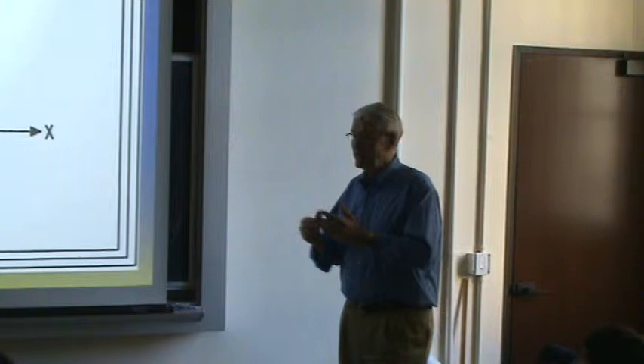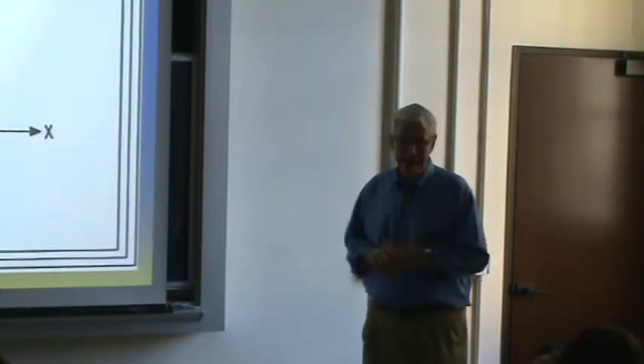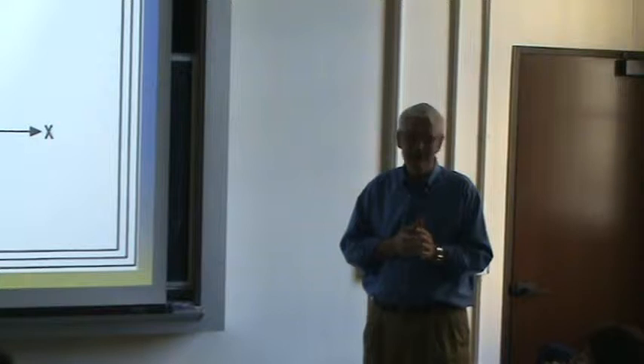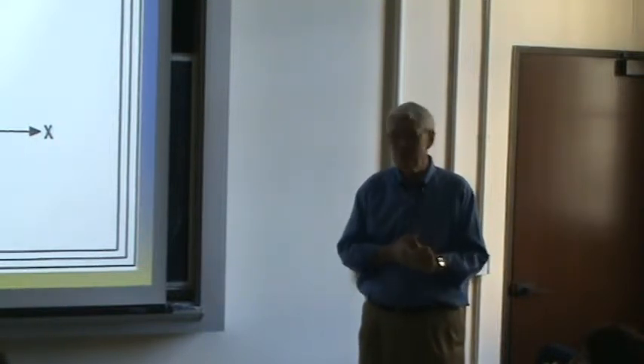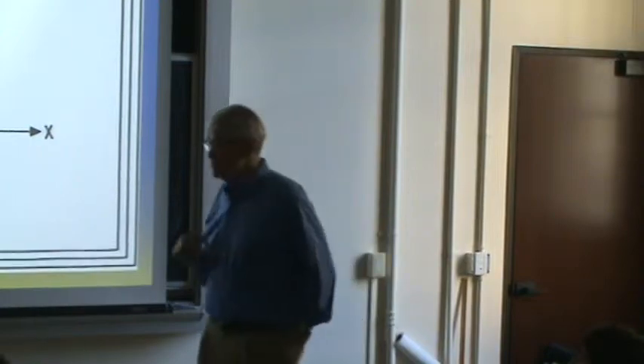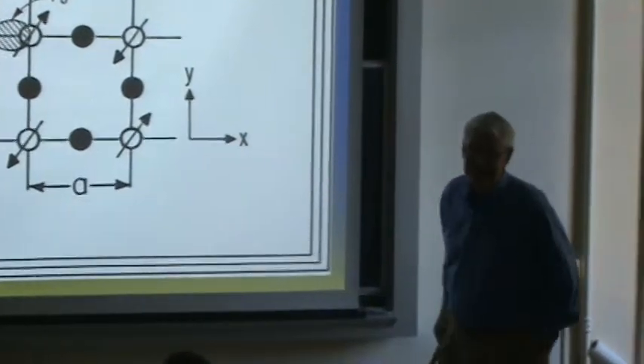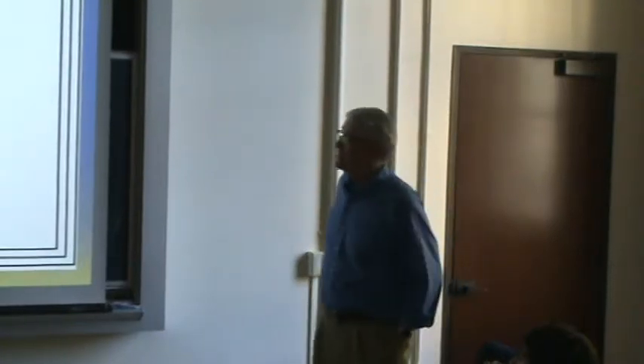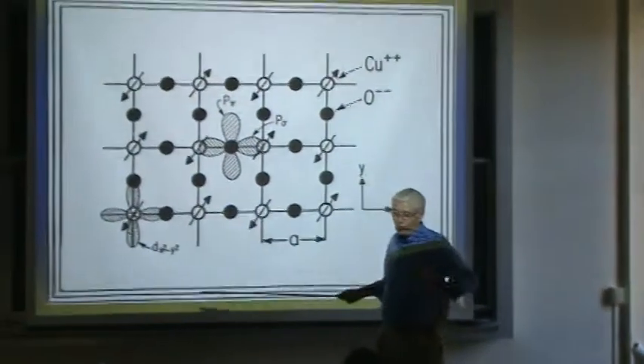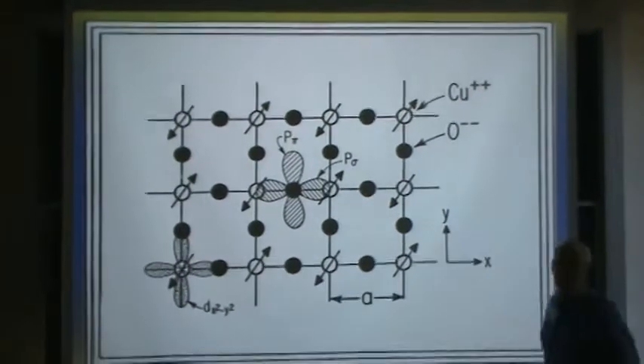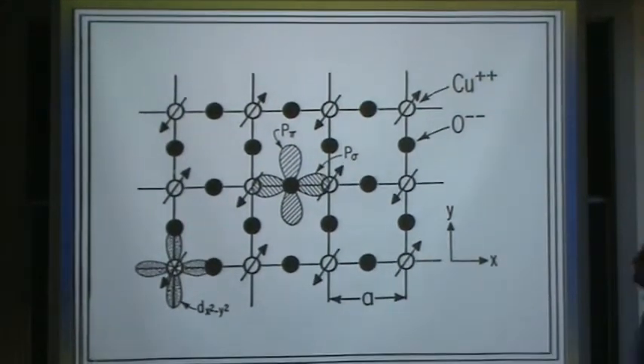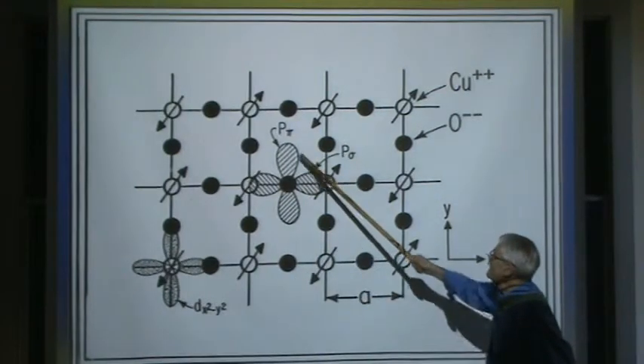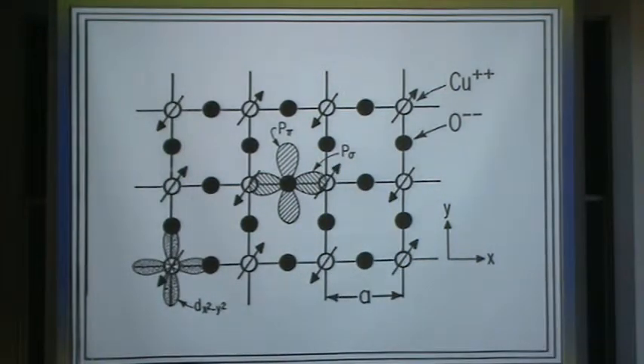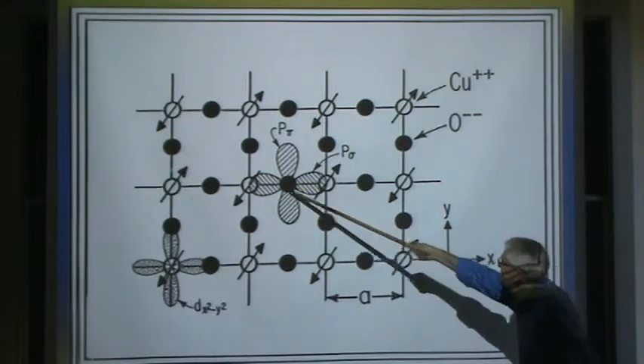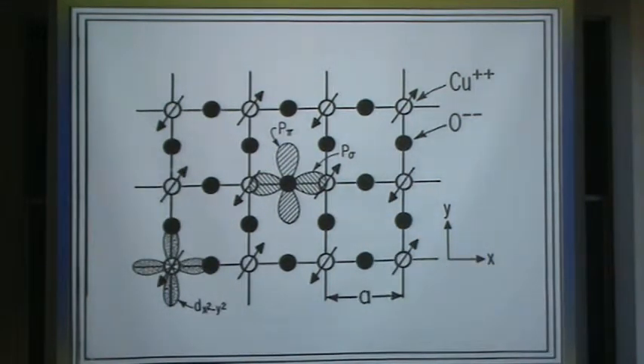So you pretty quickly convince yourself that the copper in lanthanum copper oxide, or any of these materials which form the high-temperature superconductors, has got a single hole in the d shell. And then if you do some simple electrostatics, you can convince yourself that the lowest hole orbital looks like this. This is x squared minus y squared. Then you look at the oxygen, and there are two possibilities which are close in energy, but one wins, and that's this p sigma orbital. Okay. But this is now disturbing.